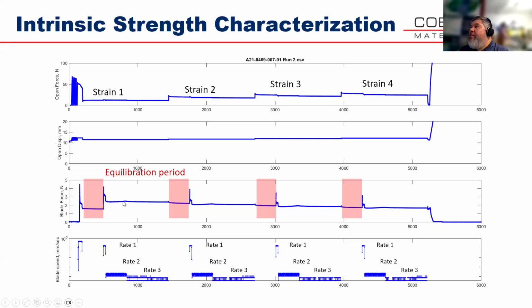And what I want you to notice is that for each of these hold periods, there's kind of two sub steps, right? So once I hit my hold strain, the first thing that happens is that the machine will stop and it will just let everything sit still for a couple of minutes, so that any viscoelastic things can die away. And so we call that the equilibration period, right? So everywhere you see a red rectangle, the machine is just sitting still, everything's equilibrating.